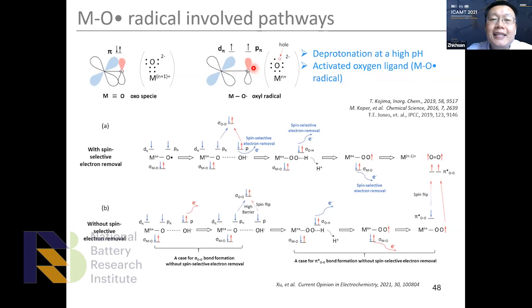So in this case, they do not form a pi bond with the metal center. Actually, they form a radical over here. In this case, the d orbital and the pi orbital of the oxygen can have electrons not in the chemical bond. In this case, their electron spin direction can be parallel. And in fact, this is true. They must be parallel. So we can see the reference paper here. So this is totally different from the OH group, the oxy species, in which they form a pi bond and then these two electrons have to be in the opposite direction in the spin.